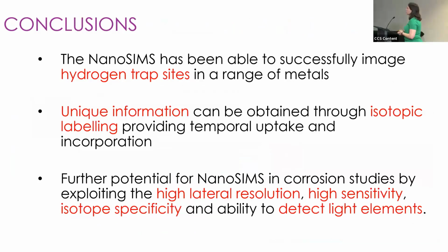So just to conclude then, I've demonstrated how the NanoSIMS has been able to successfully image hydrogen trap sites in a range of different metals, something that is very difficult and very few techniques can actually achieve. We can get some really unique information by using isotopic labeling. So we've used deuterium, oxygen-18, but you can use carbon-13, nitrogen-15. So you can get that temporal uptake indication. You can get that snapshot of what is happening at a particular point and see where in your coating or where in your oxide a particular element is incorporating.